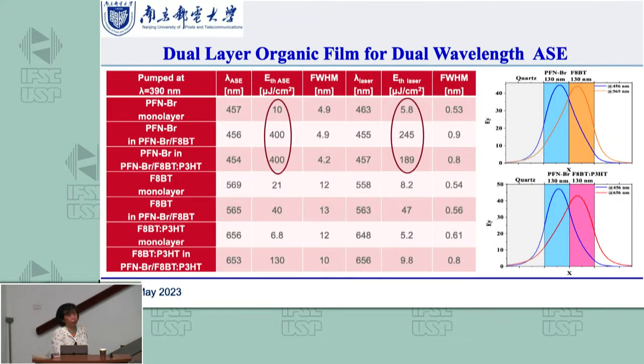This work is not quite finished because, for the blue emission laser, the threshold is still very high. Because of the waveguide losses, part of the blue emission comes out to the F8BT side and is absorbed by F8BT, so that makes the threshold increase a lot. But we know how to improve it, because we can blend the F8BT with another blue emission material to solve this problem.